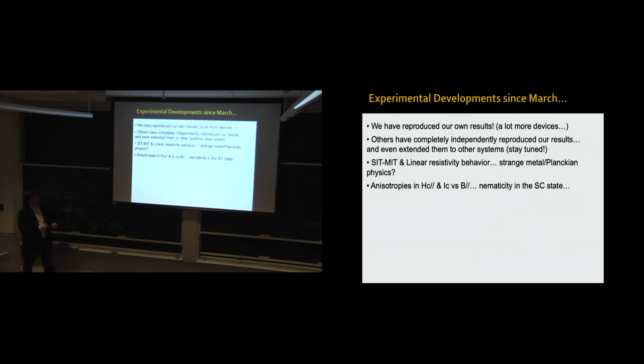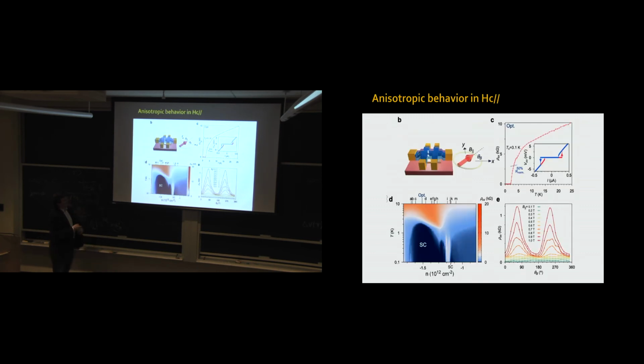We have also measured anisotropies in the critical magnetic field of the superconducting state. This means the superconducting state of our system is spontaneously breaking rotational symmetry - it chooses a direction for the order parameter. This is called nematicity. If you measure the resistivity versus angle of your in-plane magnetic field, you have two lobes, which means an ellipse in polar coordinates. Let me show you the ellipse.